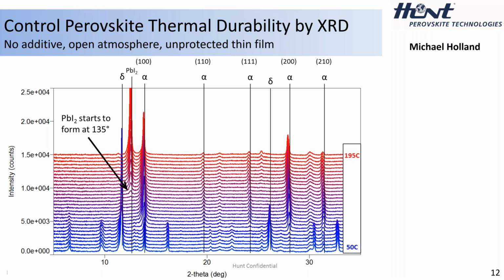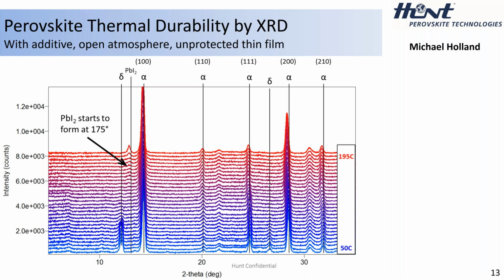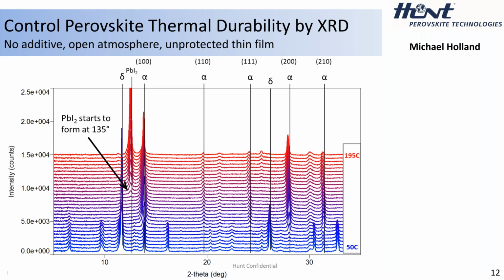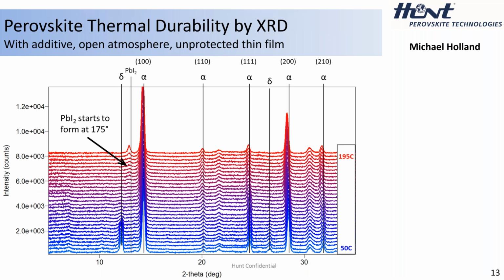But then we put this into the original ink, allowing it to incorporate into the solid, and we can heat it all the way to 195 and the material remains stable. There is a little wiggle of lead iodide there, but nothing as prominent as we see here with no additive. Again, all the peaks are highlighted and labeled across the top of the diffraction pattern, lead iodide pointed out. Big improvement, right? 195 Celsius is not a problem for this material that had previously started to have an issue at 135.